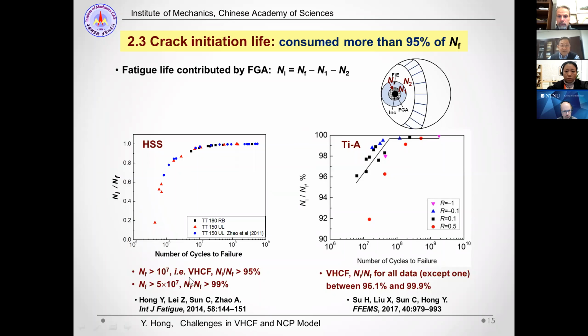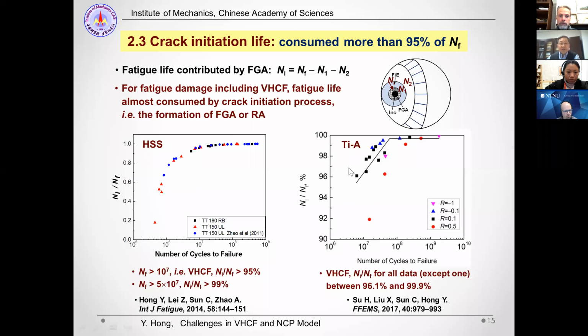This result shows that at the very high cycle fatigue regime, the initiation life is larger than 95% of total fatigue life. And if the fatigue life is 50 million cycles, the initiation life is larger than 99% of total fatigue life. And for titanium alloy, the initiation life for very high cycle fatigue is between 96 and 99%. So we can say that for fatigue damage, including very high cycle fatigue, the fatigue life is almost consumed by the crack initiation process, that is the formation of the initiation area or initiation zone of FGA or ODA.